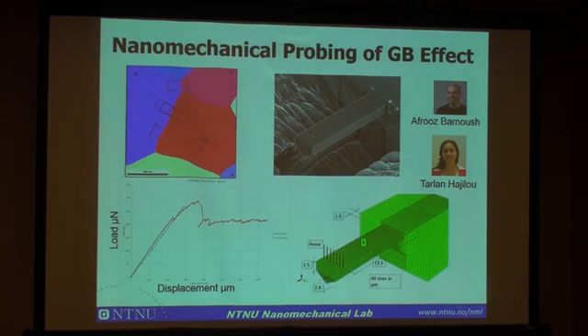This is nickel. And in addition to the DFT, we have nanomechanical probing of the grain boundary effect. So Afrooz and his students are heavily involved with nanomechanical probing. We can use EBSD to identify the grain boundary, which is of interest. Then use nanomachining, let's say FIB, focused ion beam, to cut the specimen with the intended grain boundary, and use in situ charging, and put this whole specimen into the nanoindenter, and compare with and without grain boundary, and then use the numerical models to understand the effect of grain boundary.